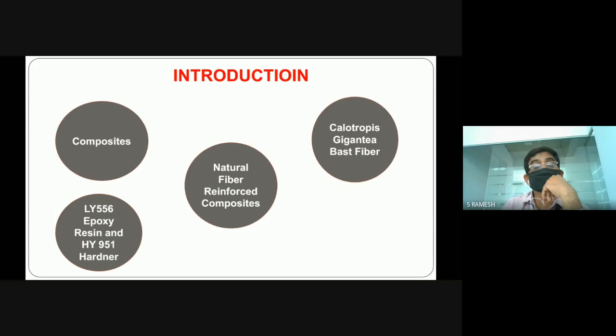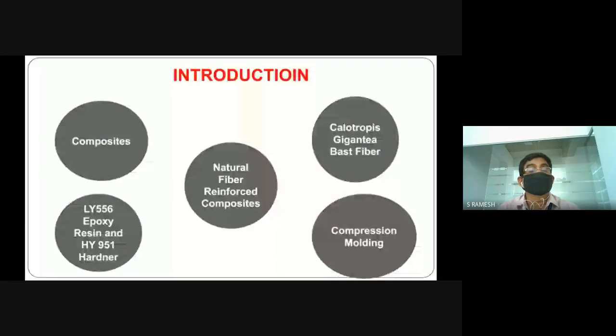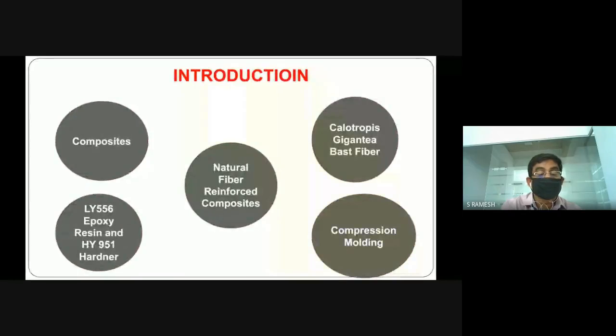We will take the HY951 hardener, which gives very high rigidity. We will do the mixture in a 50:50 ratio, and then go for compression molding. Most of the literature uses the hand layup method. We go with compression molding to get a uniform load applied during the fabrication of laminates, so we get uniform load throughout the entire composite laminate.